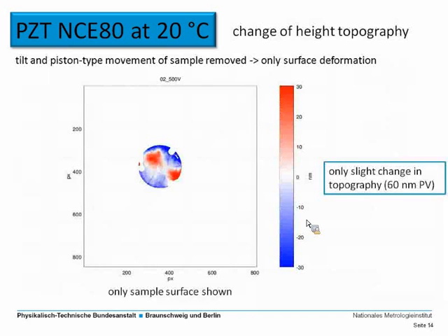But remember that we have an imaging interferometer. This was just one length value I showed you. In fact, we can see the entire sample surface at once and see what it is doing when we apply a voltage. So just to show you the sample surface deformation, I removed any piston type of movement and any tilt of the sample. Both are present as well, and the piston type movement is even the dominant part, but just to make sure what kind of bending or deformation the sample does, I removed them because this effect is rather small. So the height scale here is just 60 nanometers peak to valley.